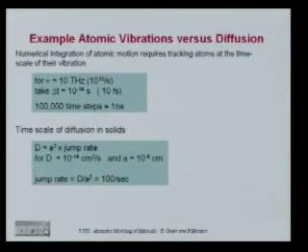If you want to do MD, the first thing you should do is a back-of-the-envelope calculation. Is the phenomenon that I want to see, or that I hope to see, living anywhere near this time scale? And sometimes you can give the system help, you can raise the temperature because stuff will happen faster. Okay? But you should realize that there's certain stuff that you do not see on this time scale at all.